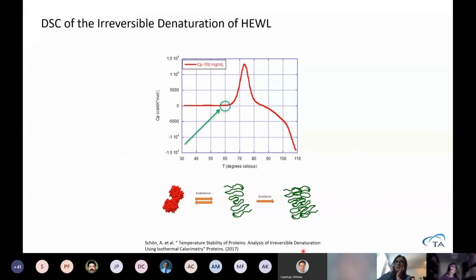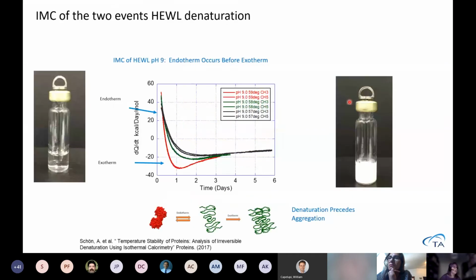So here's an example of lysozyme as a model system to test this. If we have the denaturation and then aggregation, what if we take a temperature just below the denaturation peak and put the sample in an isothermal microcalorimeter at a lower temperature and see what's going on? Is that possible? Let's see. And yes, it is possible to do that. So here they have put it at different temperature, 57, 58, and 59.